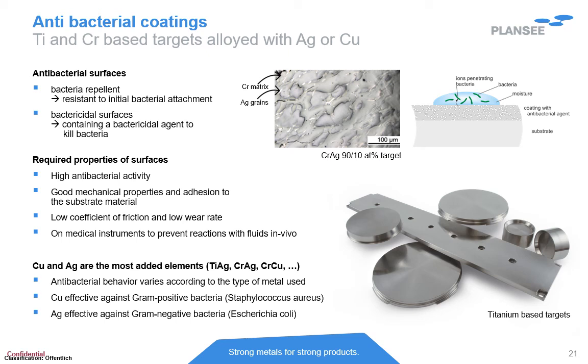The next and last example is also related to powder metallurgical production of targets with flexible compositions. In the last few months, we have been facing strong demand for targets containing small amounts of copper or silver. These elements are well known for antibacterial behavior. The direct alloying of targets with these elements seems to be the simplest way for deposition of antibacterial surfaces. In this case, you are not forced to work with co-sputtering. You can guarantee a uniform coating composition, and you can work in your PVD system with a high deposition rate. In most cases, such coatings are deposited in a reactive mode for nitrides, having not only high wear resistance, but also being active against bacteria.